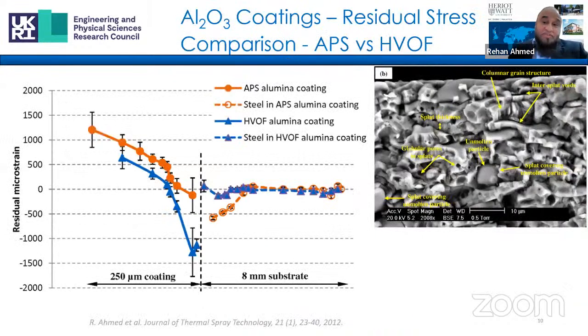And this slide gives another example of the changes in residual stress profile caused by the differences in the deposition techniques of air plasma spray and high velocity oxy-fuel spray. The measurement was done using neutron diffraction method in this particular case.